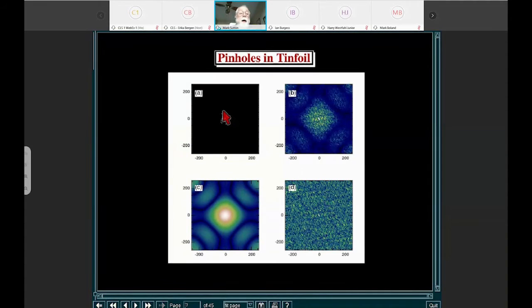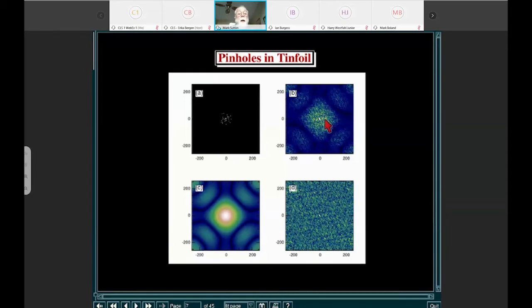Well, let's now imagine the particles move around. The speckle pattern depends in detail on the exact position of each of the particles. And so if the particles move around, the speckle pattern moves around. And therefore, by measuring the intensities of the speckles as a function of time, one can get interesting information on the motion of what the particles are doing.